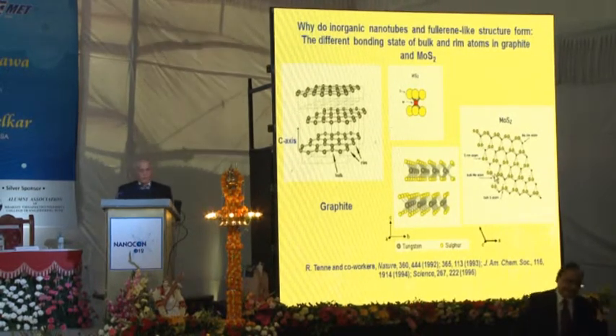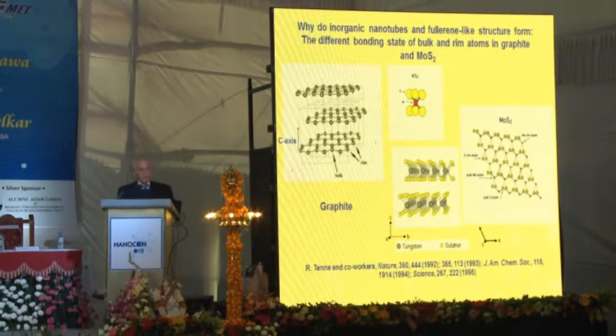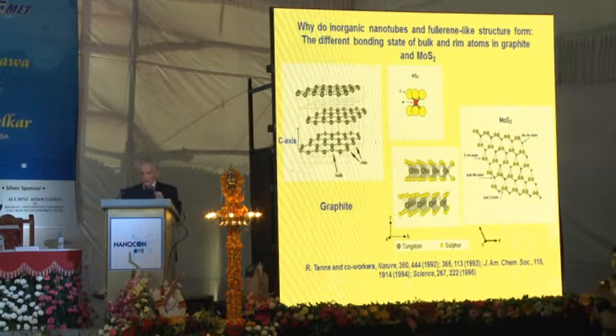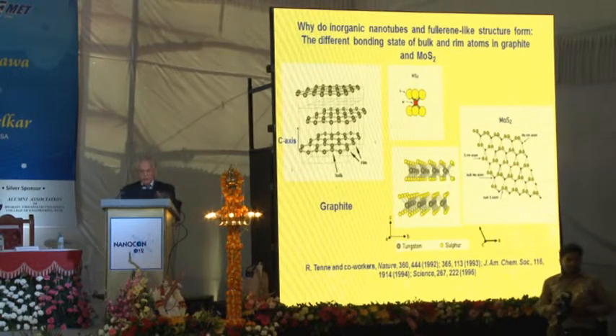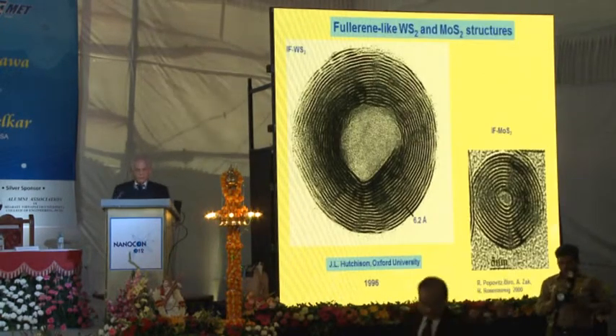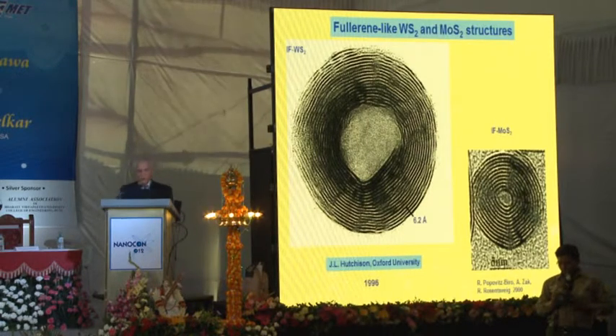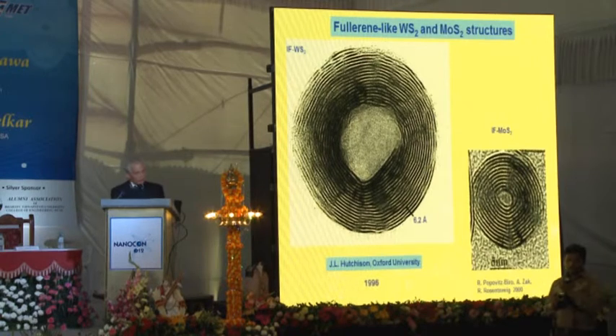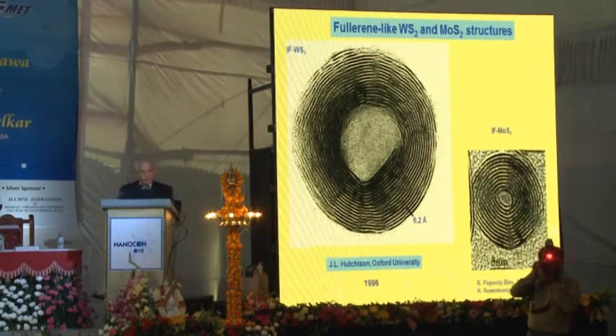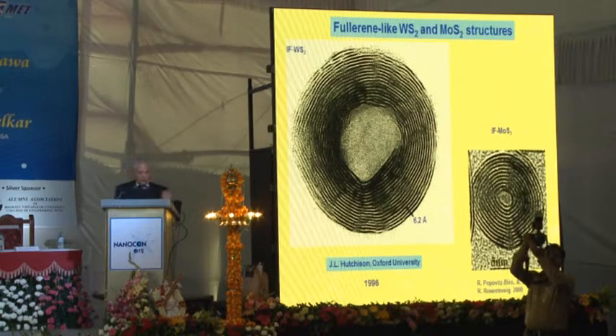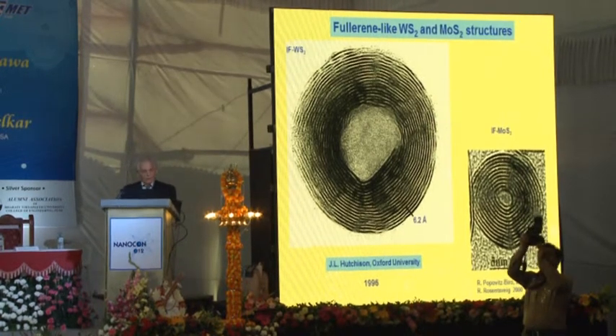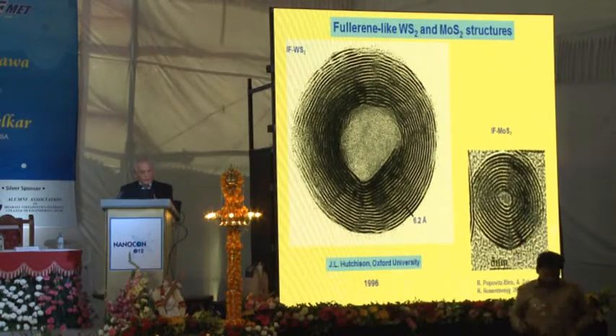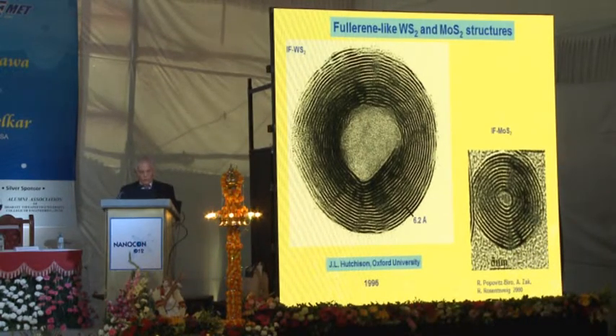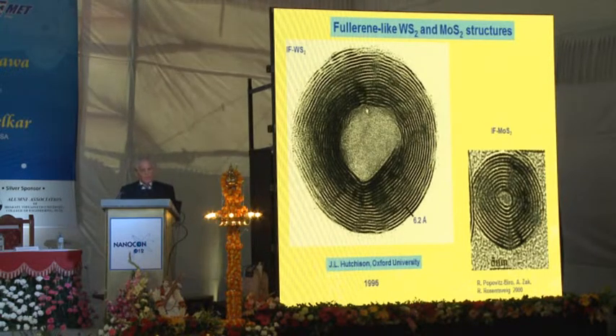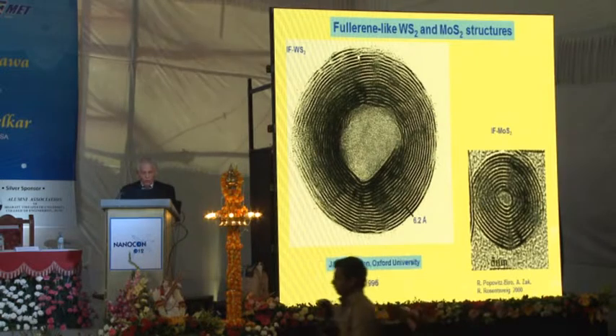So the consequence is that when you bring this structure to the nano dimension, and you have a lot of these rim atoms, the structure will not be stable in the planar form, and instead it will form structures like that. So these structures are actually hollow closed structures of tungsten disulfide and molybdenum disulfide, which we have reported in Nature in 1992 and 1993, and then in Science in 1995, which are formed by simply folding the layers and closing them into a hollow closed structure. And basically, it's a spherical wall of tungsten disulfide.